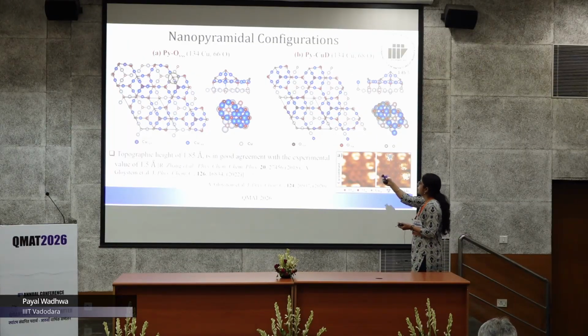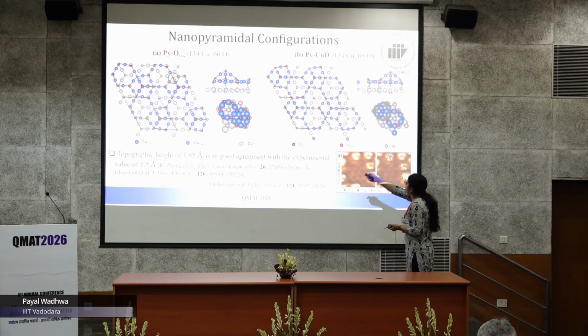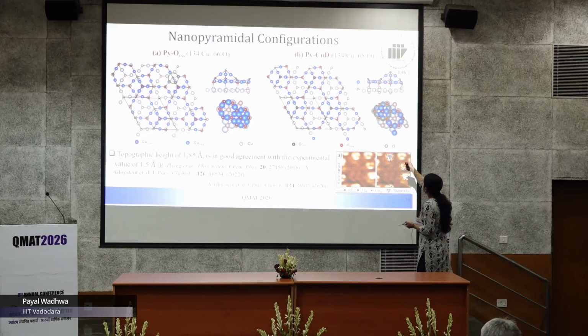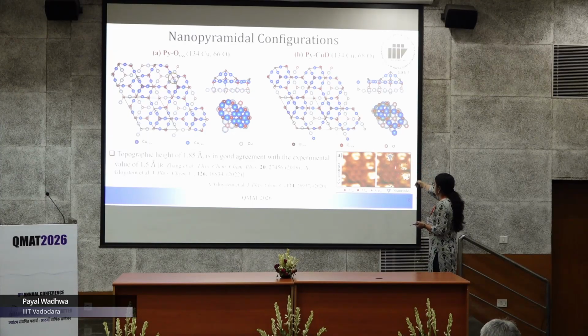Then come the nanopyramidal configurations. When we performed the parallel tempering simulation on this stoichiometry, we found a copper cluster arrangement similar to the one seen in the STM image. You can see here that there are 3 coppers in the middle. And this topographic height is also in agreement with the experimental value.